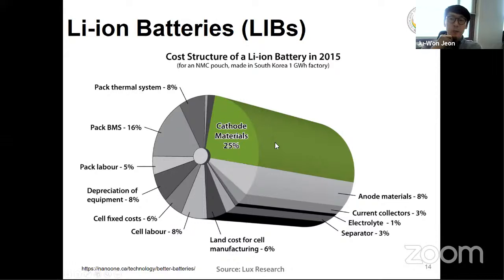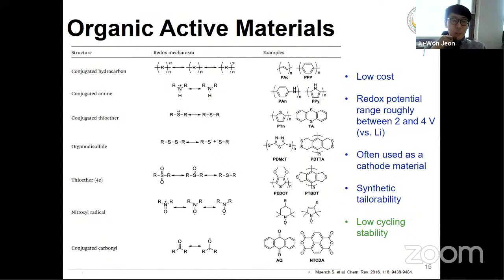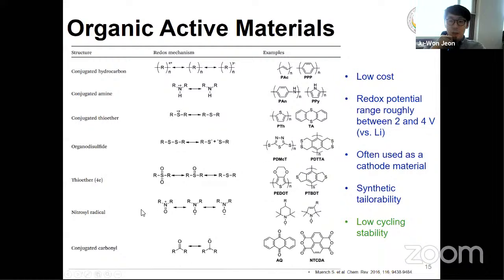So it is very important to decrease the cost of the cathode material because inorganic material itself has a high cost. So we want to lower the cost by using different organic-based electrode materials. So there are several different kinds of electrode materials we can use. These are all organic-based electroactive materials. First one is the conjugated hydrocarbons. This one has a conducting polymer structure like this, and conjugated amine. These are also conducting polymers like polyaniline and polypyrrole. And conjugated thioether can also store the charge, like polythiophene-based polymer. And disulfide can also store the charge, and thioether. And the radical polymer can also store the charge, and conjugated carbonyl can store the charge.